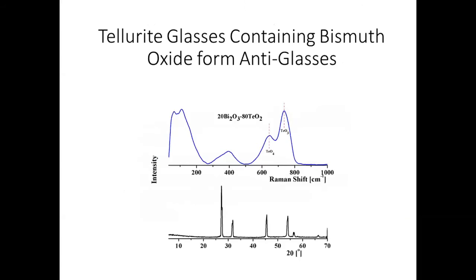If you do the Raman spectroscopy of a sample like bismuth tellurite, it forms an anti-glass phase. Its X-ray diffraction pattern shows sharp peaks, which is characteristic of a crystalline phase. But the Raman bands are fairly broad. You can see these Raman bands around 650 cm⁻¹ and around 750 cm⁻¹, and these are due to TeO4 and TeO3 units. So Raman is showing vibrational disorder. The phonons cannot propagate long distances, but the XRD patterns show ordered arrangement, and the ordered arrangement is only that of the cations, like bismuth and tellurium ions in this case.